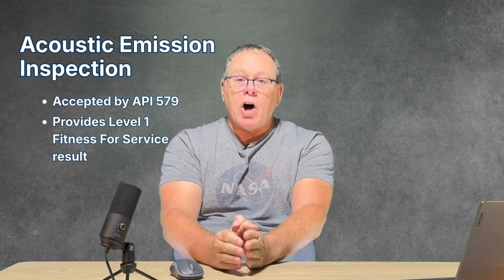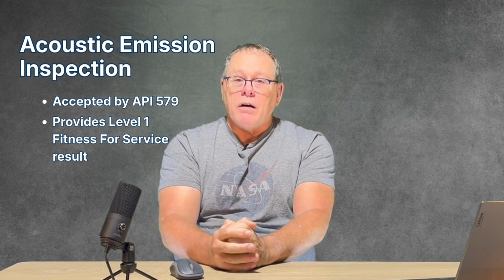AE testing will always provide a level 1 fitness for service result. There are some features about it that make it a little more difficult, but here's what they are. It doesn't give information to actually determine remaining strength factor. It only provides a fit for service or not fit for service result. And as a consequence, if it's fit for service, it also cannot provide any information that allows us to determine remaining life. Those are some limitations of acoustic emission testing, but it is still a completely valid way to determine fitness for service of FRP equipment.